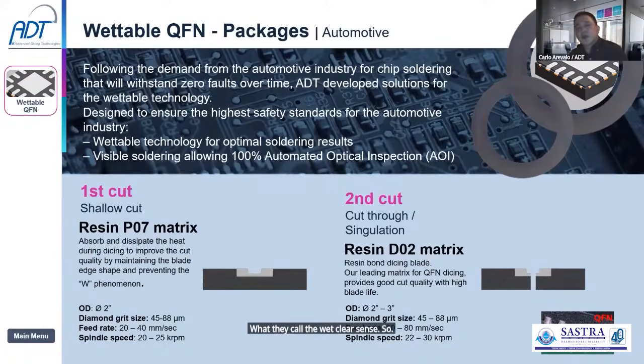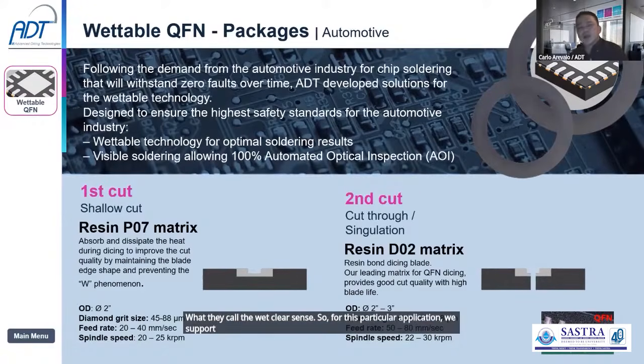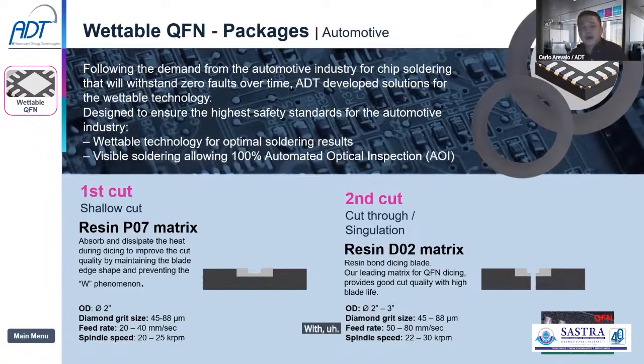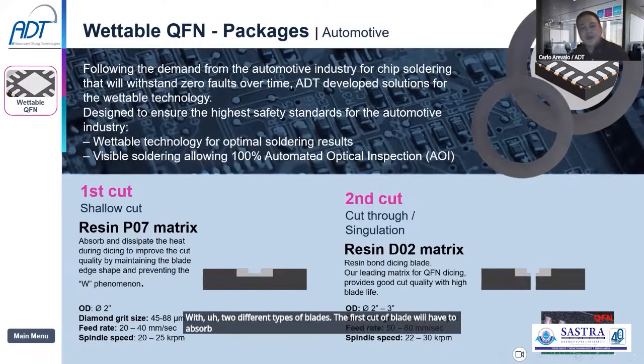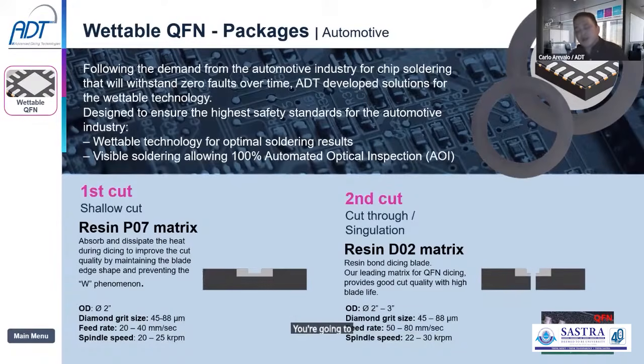So for this particular application, we support this type of application with two different types of blades. The first cut blade will have to absorb or dissipate the heat because you're going to half cut or do a shallow cut on the leads for the first blade. And normally there's a lot of loading because of the plating material as well. So the blade that we recommend is what we call the P07 matrix, with the diamond range of 45 to 88, a feed rate of 20 to 40. So you are just cutting slightly half of the thickness of the leads.